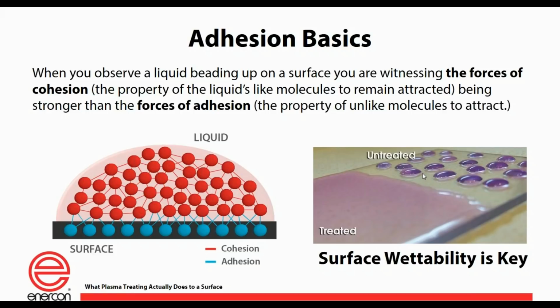With our methods, with plasma and with flame, you are going to increase that adhesive bond. You're increasing those polar groups, you're increasing that surface energy, and you're going to see the water wet out as it does there on the left side of the other picture. So these are the forces that are in play, and these are what affect your surface energy and whether or not you're going to get a good coating, good adhesion or good printing.